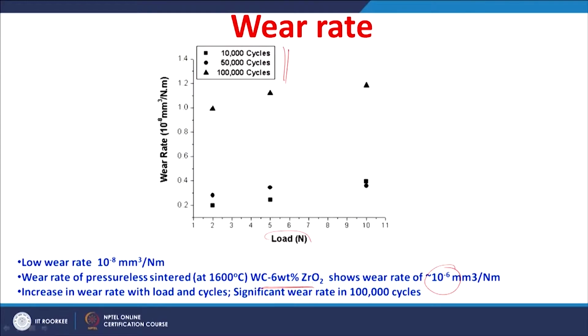So, this is a very low wear rate as you compare with the wear rate obtained with the conventionally sintered tungsten carbide 6% zirconia ceramic. That shows 10 power minus 6 mm³ per Newton meter, whereas the spark plasma sintered tungsten carbide zirconia nano ceramic composite exhibited a wear rate of 10 power minus 8 mm³ per Newton meter. An increase in wear rate is also observed with increase in the load as well as the cycles.